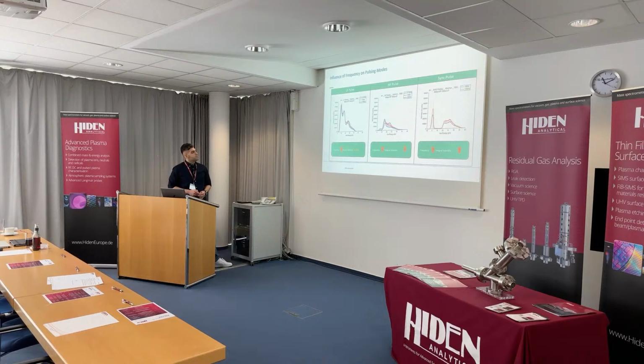This is the influence of frequency on different pulsing modes. In case of LF pulse, as the frequency increases from 0.1 kHz to 10 kHz, the integral intensity almost remains constant. In case of HF pulsing, increasing the frequency has an impact of lower integral intensity. And in case of sync pulsing, increasing the frequency has an impact of higher integral intensity. So the IDFs are here.